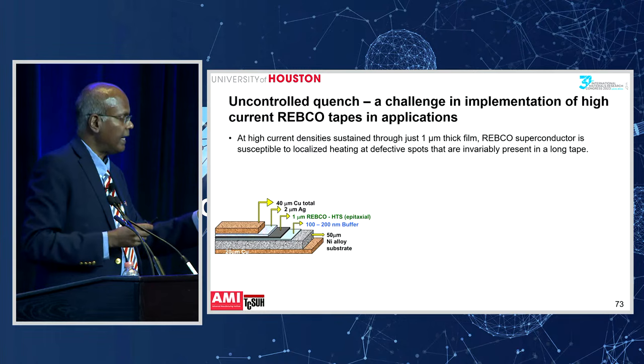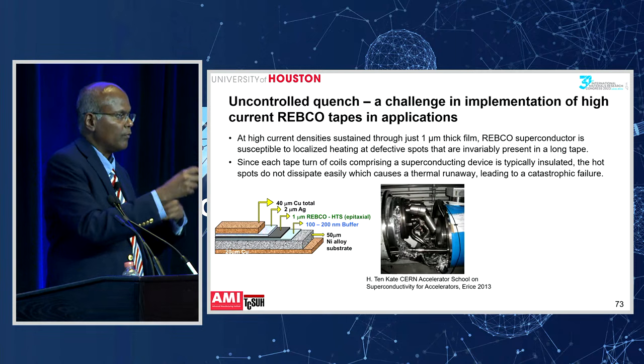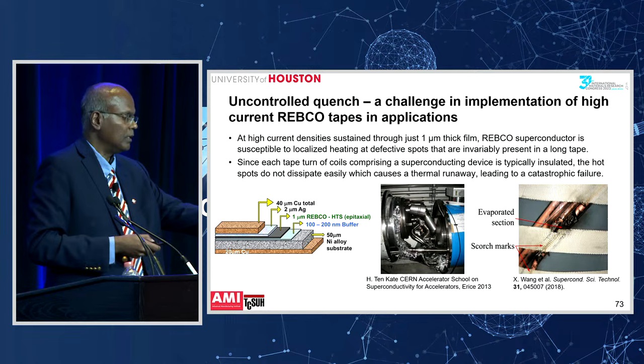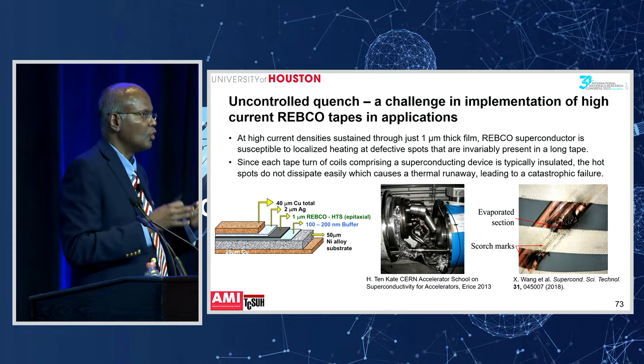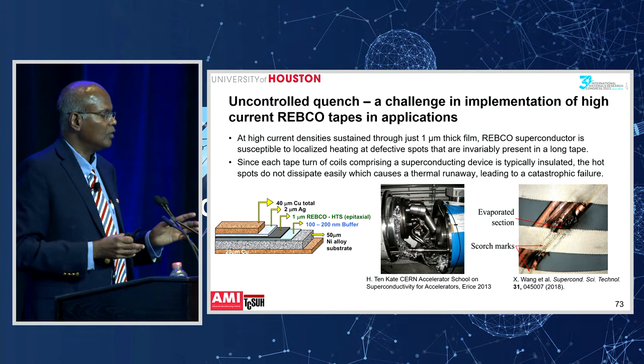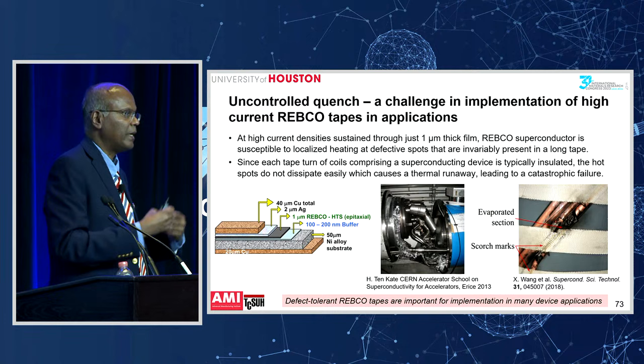Once it heats up, since you are winding the magnets, and the magnets are insulated, the whole magnet can break down. So you can see the burnout of a magnet, and in this case, a cable, because so much energy is being dumped into that area, it completely burns out. So you need to have a way to prevent the thermal runaway, and basically you need what you call defect-tolerant tapes, self-healing tapes, tapes that, in spite of defects, can still heal themselves. So that's still an area that needs to be developed.